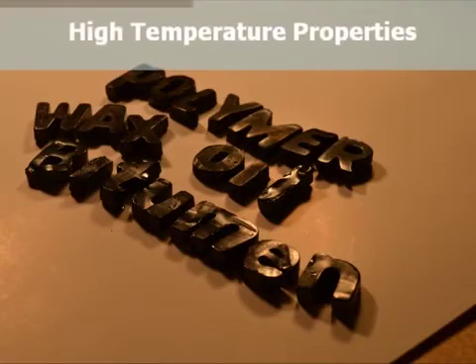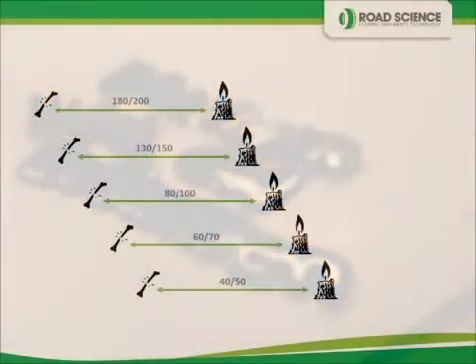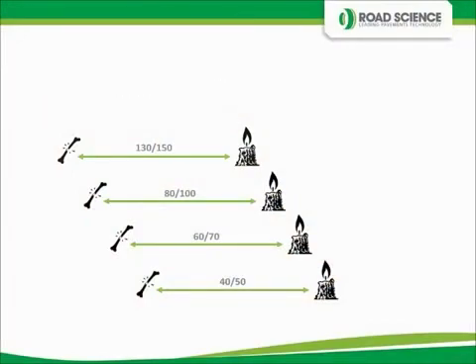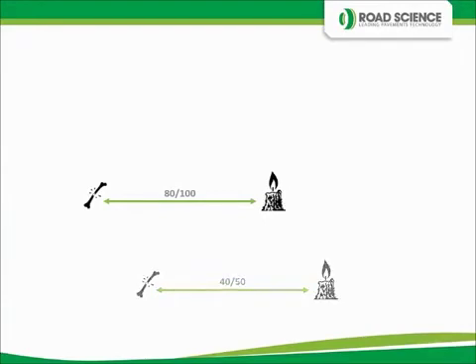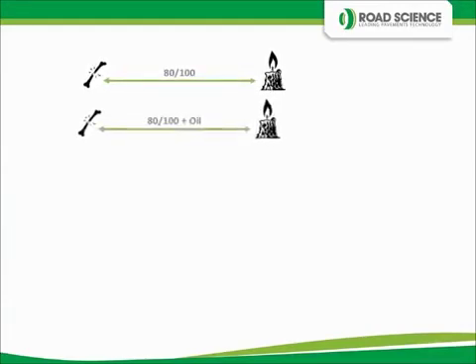To demonstrate the effect these modifiers have on the high temperature properties of a bitumen, I've placed them all under a heat lamp. As this test progresses, we can see some of them starting to melt. The bitumen modified with oil is melting the fastest, followed by the plain bitumen sample. If you look at the wax and the polymer samples, they haven't melted at all under this heat.